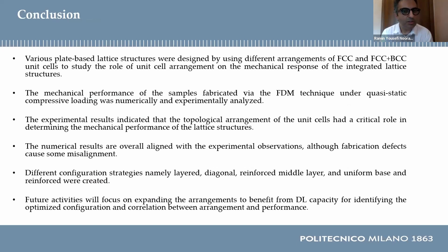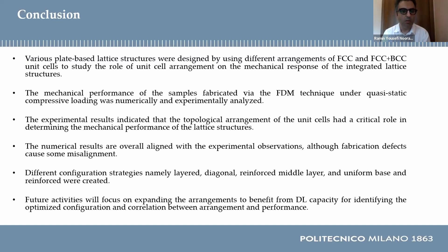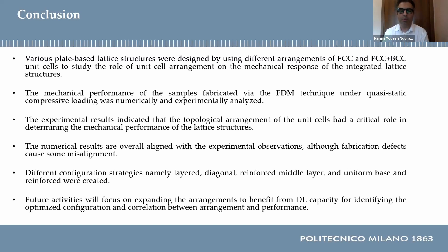Various plate-based structures were designed using different arrangements of FCC and FCC plus BCC unit cells. The study investigated how unit cell arrangements affect the mechanical response of the integrated lattice structures. The mechanical performance of the samples was evaluated using the FDM technique under quasi-static compressive loading, while being numerically and experimentally analyzed. The experimental results indicated that the topological arrangement of the unit cells had a critical role in determining the mechanical performance of the lattice structure. The numerical results are well-aligned with the experimental observations, while fabrication defects caused some misalignment.